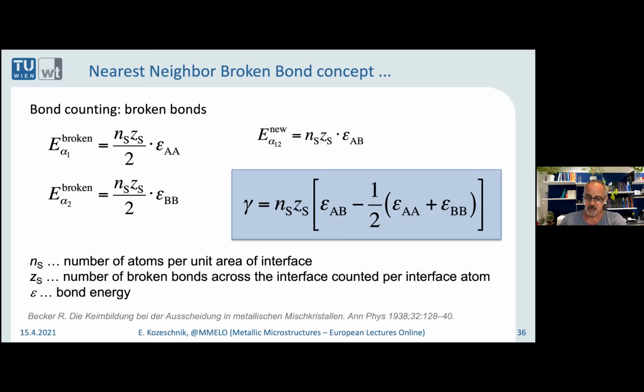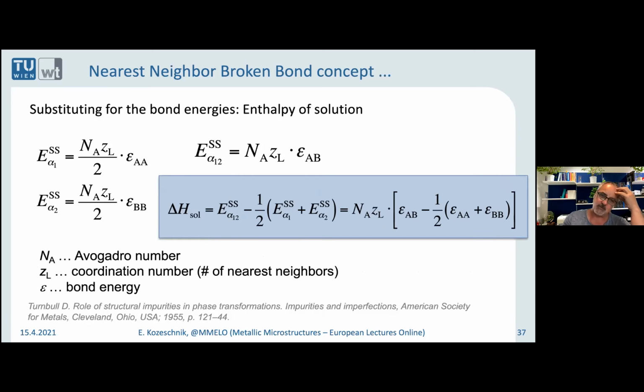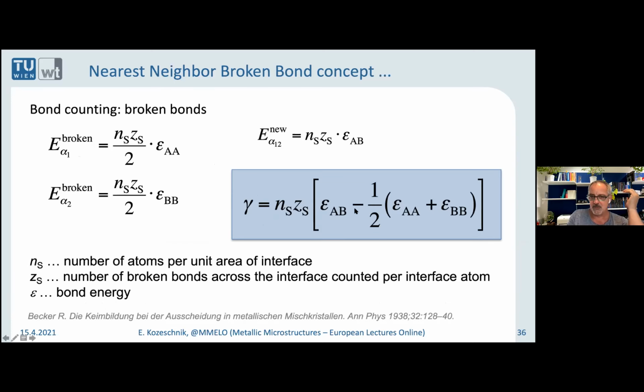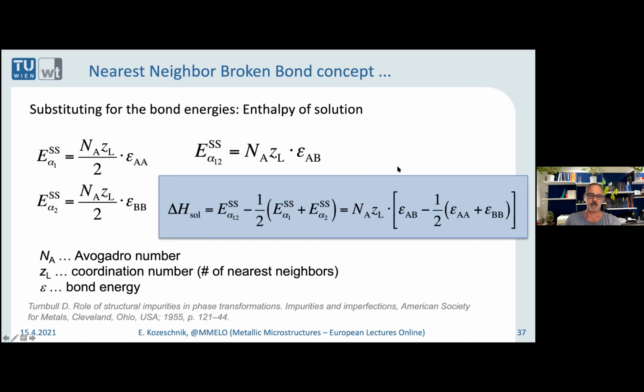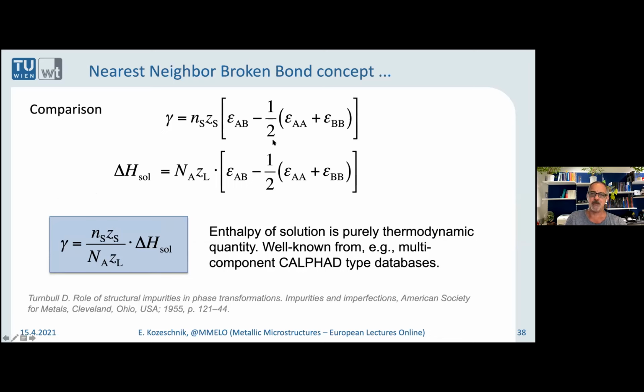It took a few decades more until David Turnbull suggested that this nasty term with the epsilons can actually be replaced by a thermodynamic quantity. He used the same bond counting strategy to evaluate the enthalpy of solution, delta H sol. He ended up with an expression that is also a structural factor, Avogadro number and coordination number, and the same nasty term in terms of the binding energies. When you take these two equations, you can get rid of the epsilon parts, and you end up with a description where the interface energy is only related to the enthalpy of solution. That we do know from CALPHAD databases, from computational thermodynamics. So that was in 1955.